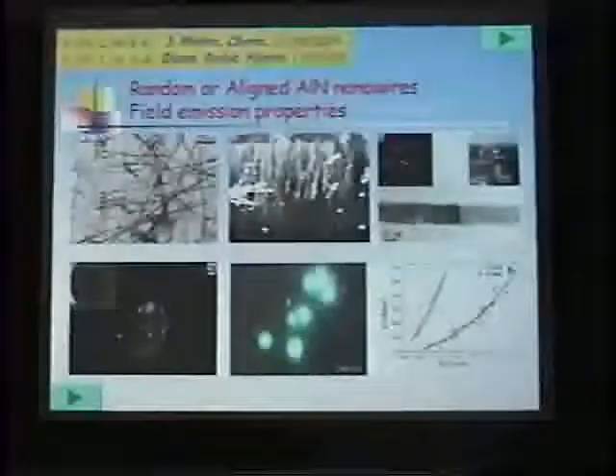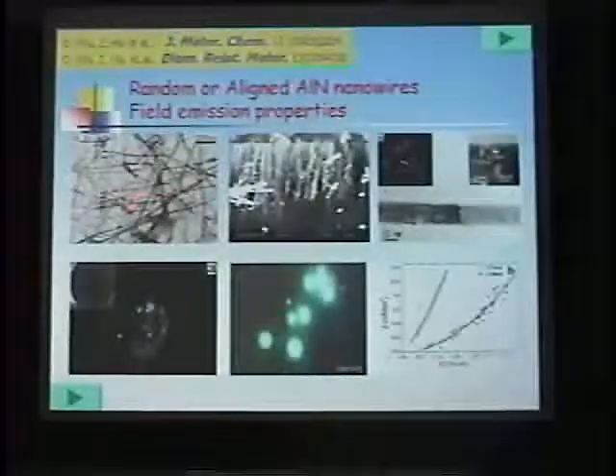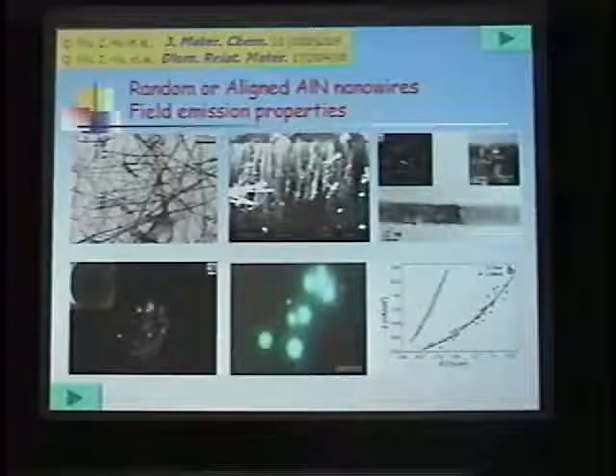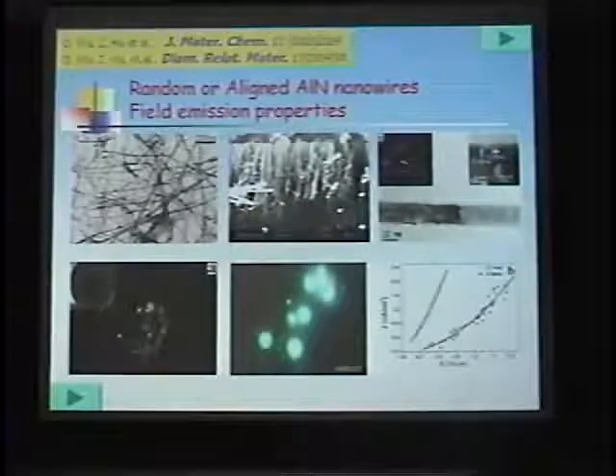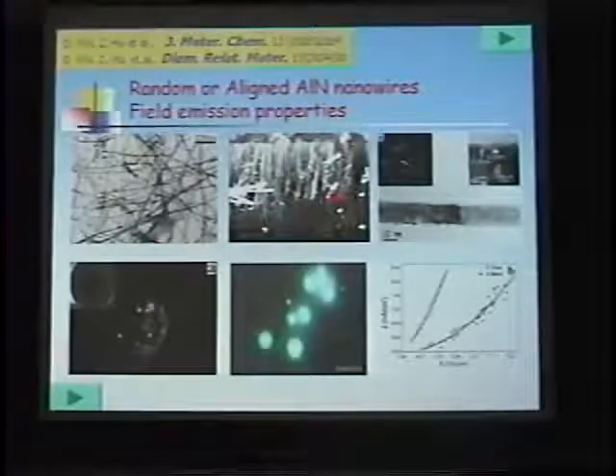By changing the reaction temperature, we could also get some random or aligned aluminum nitride nanowires, and it looks like that. This is random aluminum nitride, and if we use porous aluminum as a template, then we could align the nanowires in such a fashion.